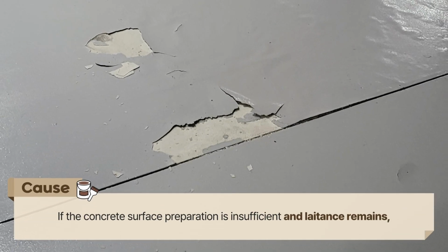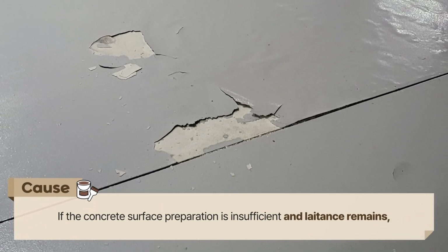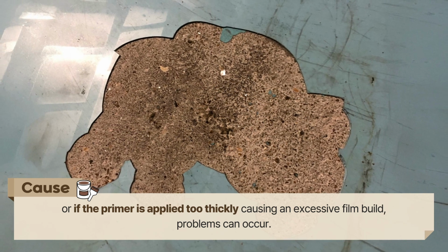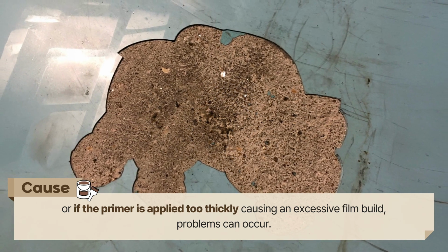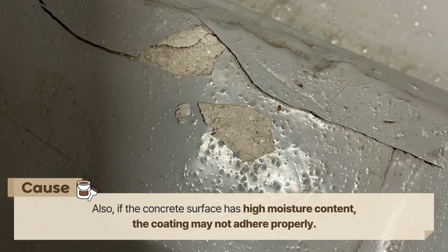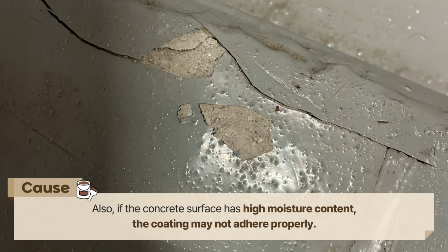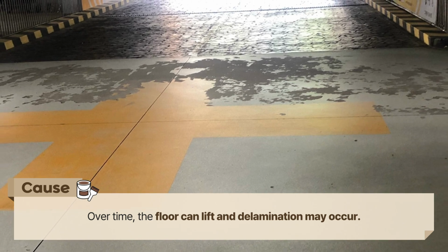If concrete surface preparation is insufficient and laitance remains, or if the primer is applied too thickly, problems can occur. Also, if the concrete surface has high moisture content, the coating may not adhere properly, leading to lifting and peeling over time.